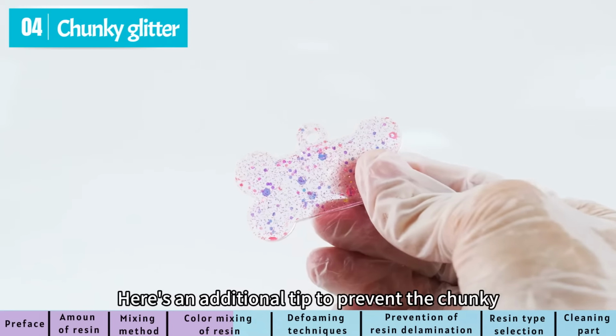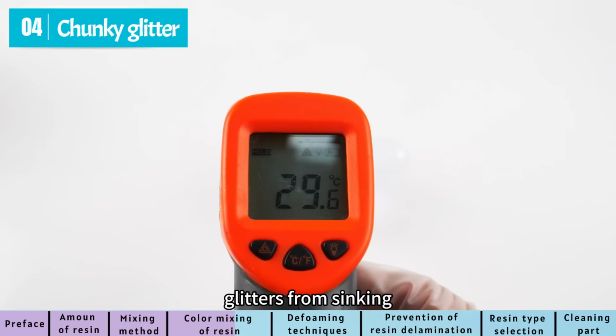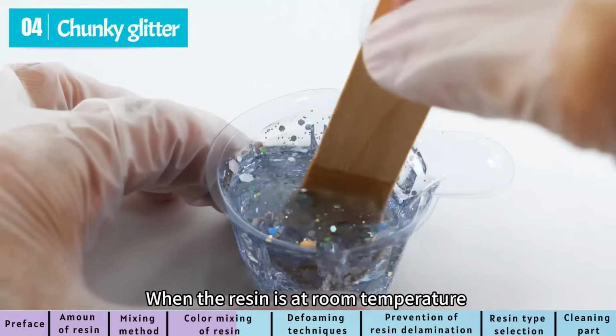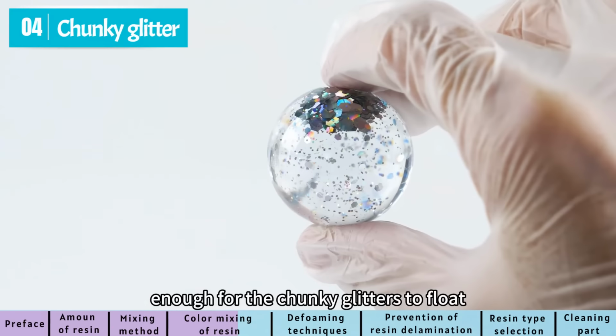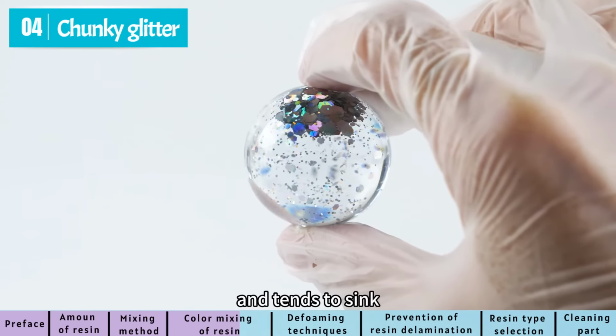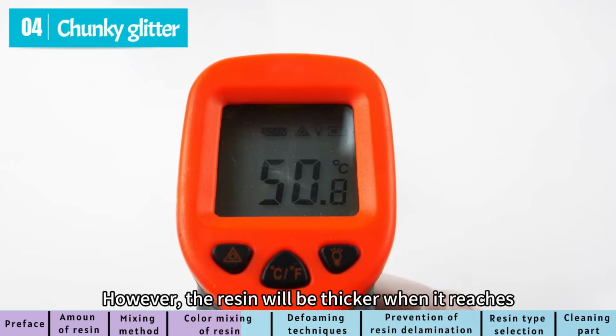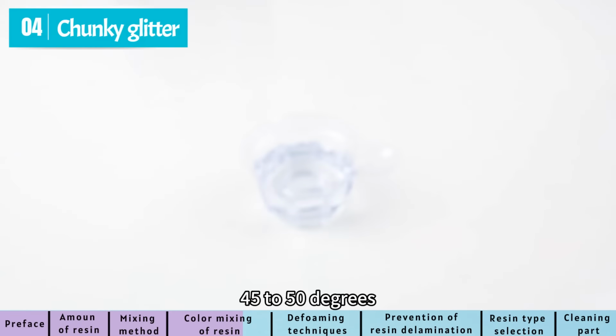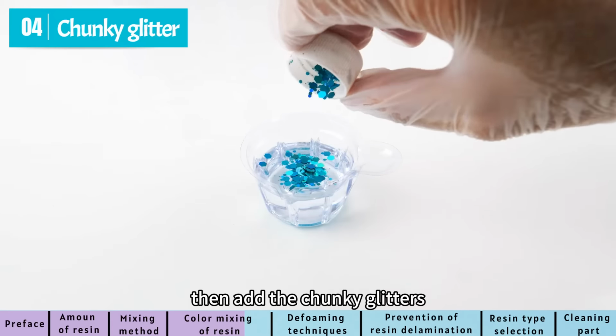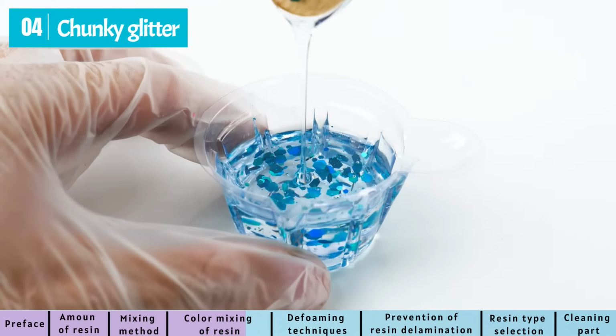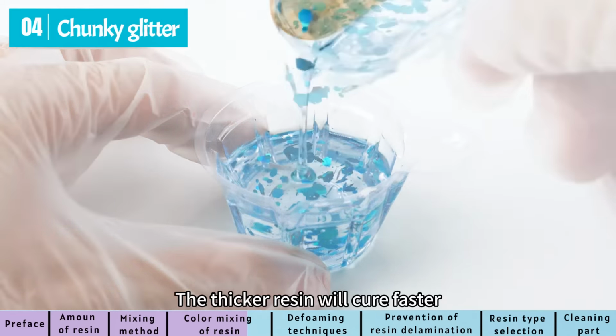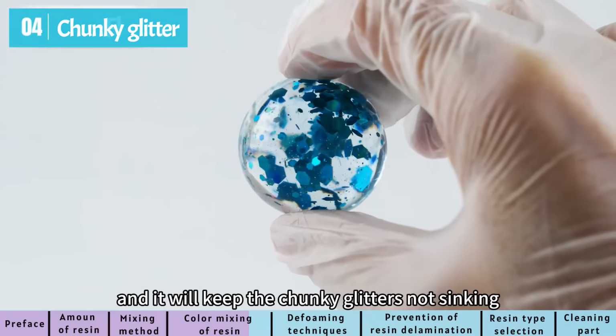Here's an additional tip to prevent the chunky glitters from sinking. When the resin is at room temperature, it is not thick enough for the chunky glitters to float and tends to sink. However, the resin will be thicker when it reaches 45 to 50 degrees. Then add the chunky glitters. The thicker resin will cure faster and it will keep the chunky glitters not sinking.